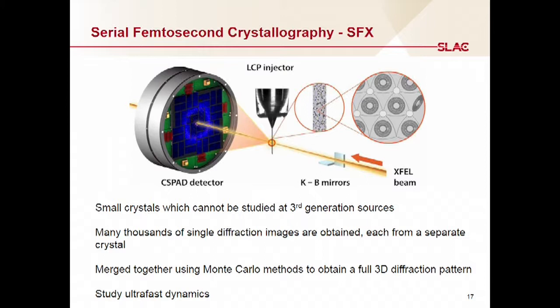which cannot be grown to larger size. But more excitingly, we can also study ultrafast dynamics. What this means is that if you want to excite one of these crystals, let's say you can pump it with an optical laser and see some kind of change. But the smaller crystals really do give you an advantage, in that you can excite the entire crystal.